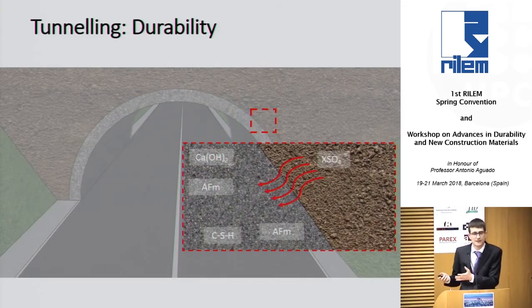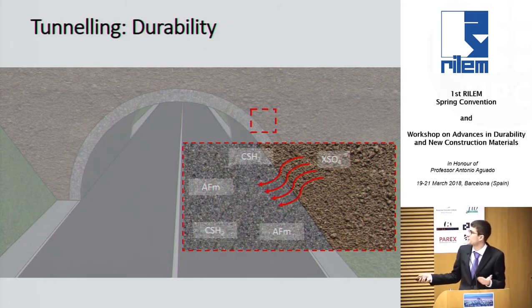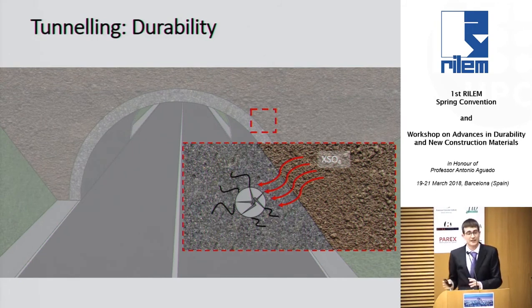And the sulfate attack is a process in which the sulfates come from the outside. They are going to attack some of the components of our concrete. So first, probably Portlandite transforming into secondary gypsum, then it's going to transform AFm into ettringite, and the transformation of AFm into ettringite is a very expansive reaction, producing cracks, generating problems.